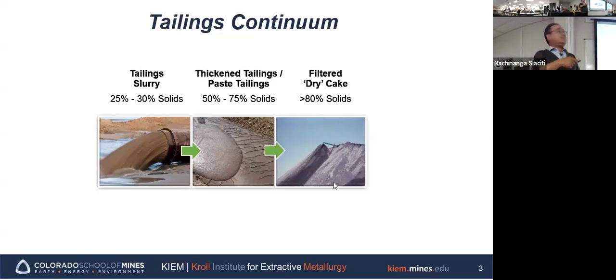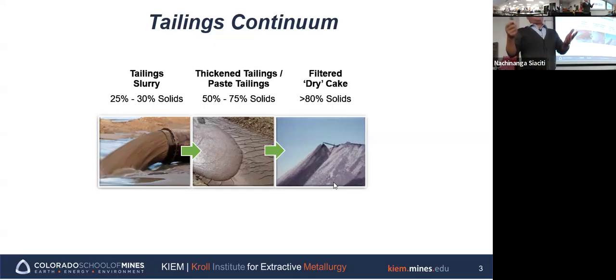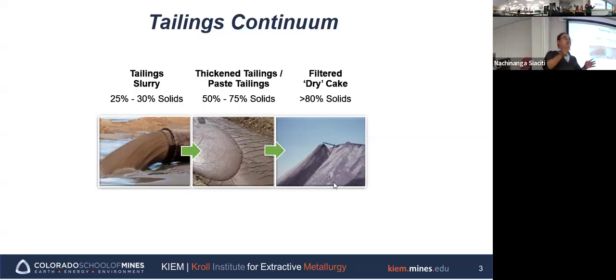So majorities are water. So if we discharge this into the tailing pond, we need more space and area to store not only the solid, but also the water. So we wanted to decrease the water portion. So we make this kind of a paste. So it looks like a toothpaste. So it flows a little differently, but it still contains 25–30% water. So it's much better, but if we can squeeze out more water, we can make what we call dry stack or dry tailing. But dry stack is not bone dry. There's still around 15% moisture in the dry stack. So that's a transition between old days and these days, new application.